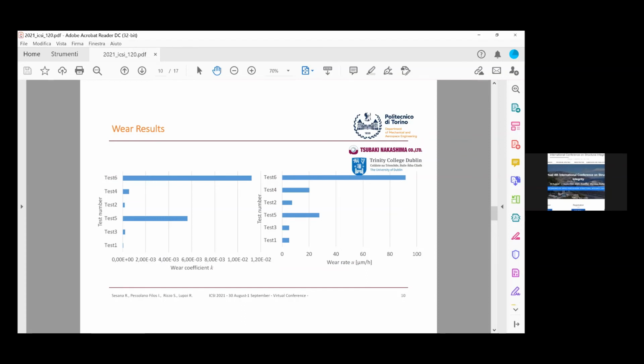Figures in the slide show the wear coefficient and the wear rates of the silicon nitride balls used during the test. It is evident that the D30 coating, which has a higher surface roughness value than the DMMC, performs a strong adhesive action on the balls. In the figure, it can be observed that the wear coefficient K increases with the increasing sliding linear speed. In fact, according to the model, all the parameters are constant for different testing conditions, and the variable is the abraded volume, which increases with increasing local linear speed.